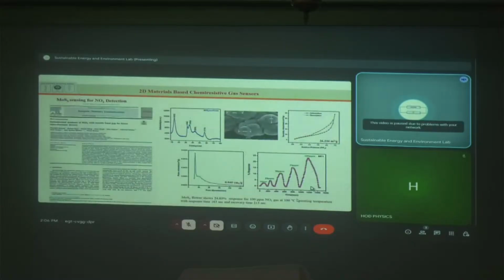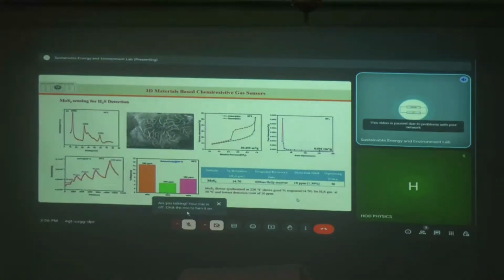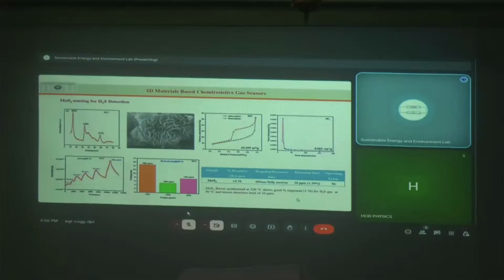Here we designed a 2D material MoS2 for NO2 detection, and at an operating temperature of 100 degrees centigrade, we reported a 24% response of the MoS2 cloud-like structure for detection of NO2 gas at 100 centigrade. Another material is also designed MoS2. We just changed the reaction temperature, and this same material MoS2 can be used to detect H2S gas, with a response of 14%.